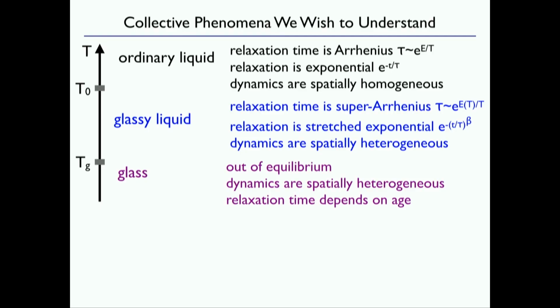It starts slowing down. That's what I mean. The dynamics just shoot up. Okay, the stress relaxation time just shoots up very rapidly. They really slow down. Okay, the relaxation as a function of time still depends on this time scale, but it becomes a stretched exponential. Okay, not exponential. And the dynamics become spatially heterogeneous. A very similar thing, actually, and it's not so different in terms of the physics, is traffic, right?